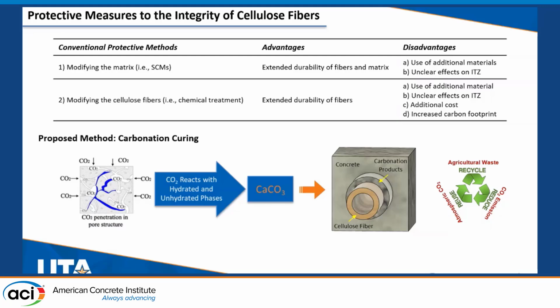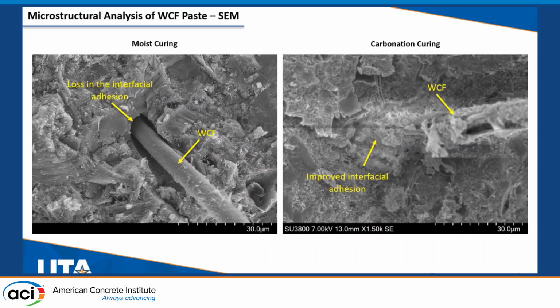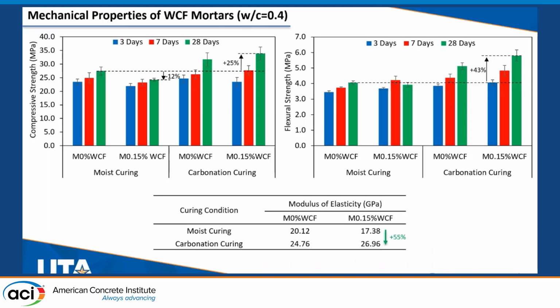This way, carbon dioxide penetrates within the pore structure of the material and reacts with hydrated and anhydrous phases of cement to produce calcium carbonate. This newly generated calcium carbonate serves to occupy the gaps between the fibers and the matrix to improve the interfacial adhesion as well as protecting the fibers from disintegration. Our SEM observations prove this, such that the loss in the interfacial adhesion in a moist cured sample is completely filled with products after carbonation curing, which results in improvements in mechanical properties.